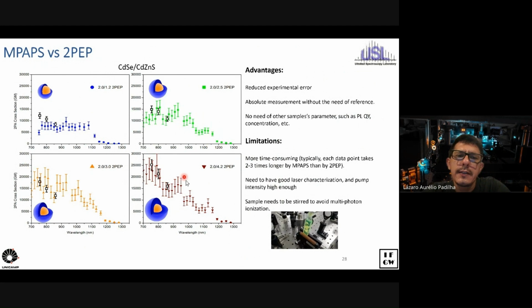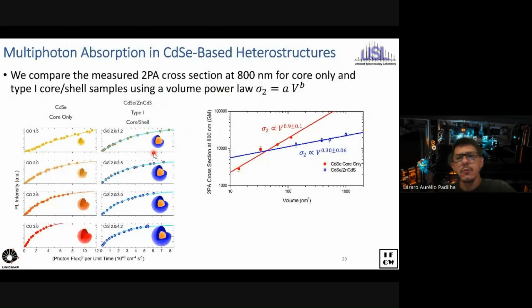And now for our technique, you really need to know your laser. You need to stir your sample because you have to avoid photoionization, which may happen because you're saturating, you're hitting it with too much photon flux. So those limitations, in fact, make it more difficult to go further, but for these regions, this technique is quite powerful. So we have used this technique to look at different samples.